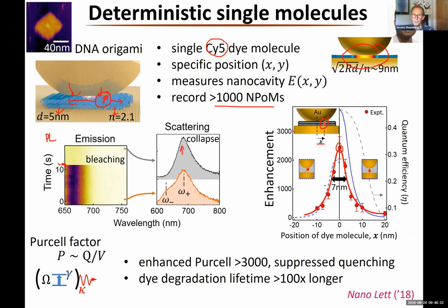And what you can see is that we're actually measuring a big enhancement here. What we're in fact doing is we're measuring exactly this optical field enhancement laterally. And I showed you before, it was essentially given by the square root of the diameter of the nanoparticle and the thickness of the gap. So on the order of about 10 nanometers. So that's basically what we measure here. So it's surprising it's so good. I mean, it's not obvious that this DNA origami structure can control the position to within a nanometer. But that's what seems to be going on here.